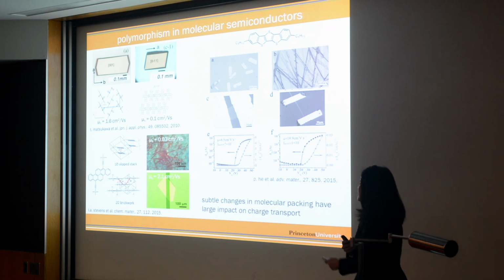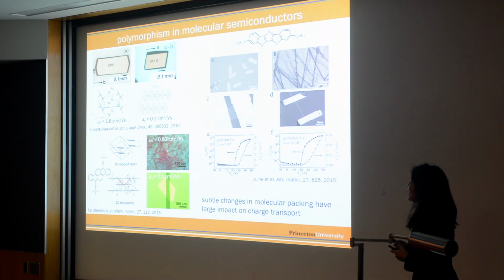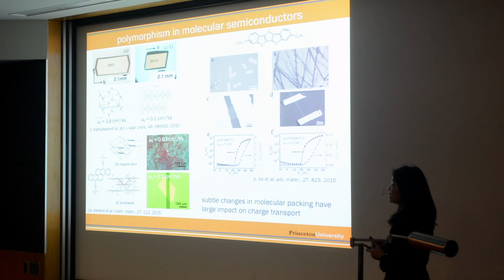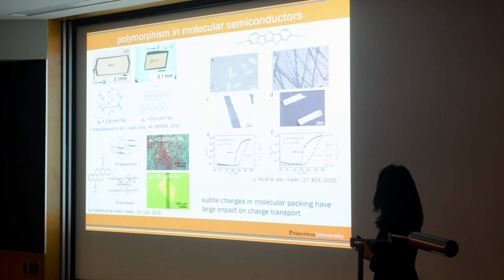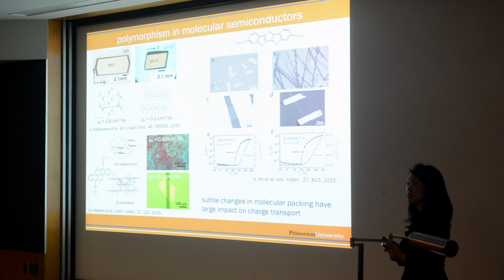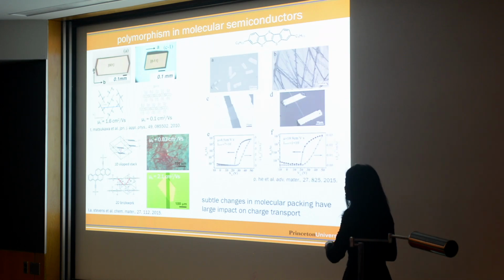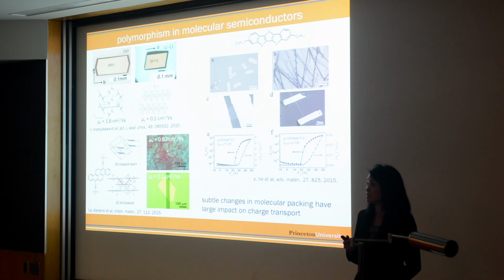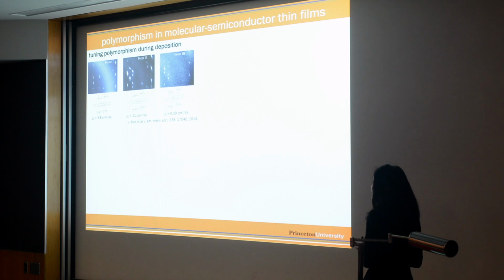This is this compound here that Wenping Hu's group makes in China. And again, you see two different crystal habits, two different distinct polymorphs. You can again make single crystal transistors with this. And again, you see big differences in charge transport, right? So subtle changes in molecular packing lead to big changes in the extent of charge transport. And this is true in thin films as well.